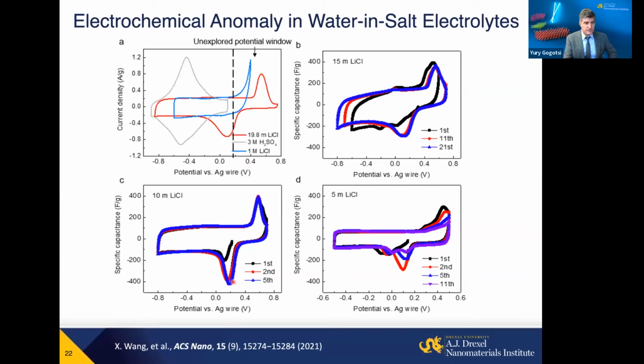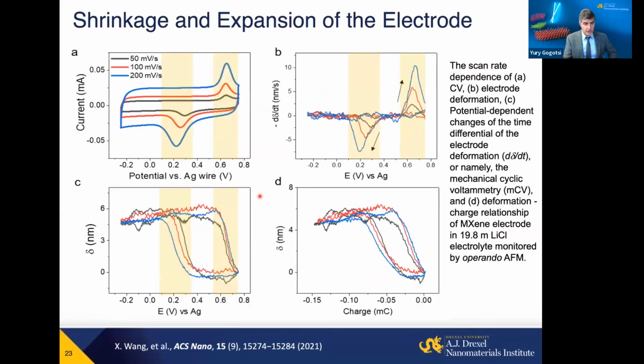However, what is interesting, we observe in this case a couple of peaks now, which are in the range of positive potential. For a typical battery material, one would say, look, it's a reversible redox process. We have two peaks on charge discharge, which are redox. However, what is interesting, when we looked at mechanics of the electrodes, we found that these peaks actually correspond not to a conventional redox process. They correspond to ions with solvent being completely removed from between the electrode layers and collapse, closure of MXene layers, and after that reinsertion. So we have processes which express themselves like a battery-like redox in cyclic voltammograms, but in fact are different.